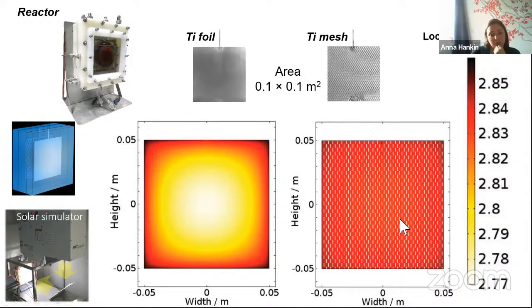And what we showed was that indeed, when you have a suboptimally oriented solid electrode, despite the fact that you have a conductive substrate, so titanium, you still get a non-uniform current density distribution across the electrode surface, even in a solution as highly conductive as a molar hydroxide, which is what we used. And with the perforations, this became homogenized greatly.